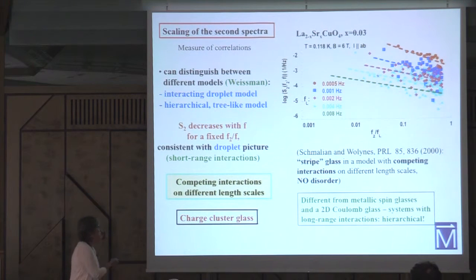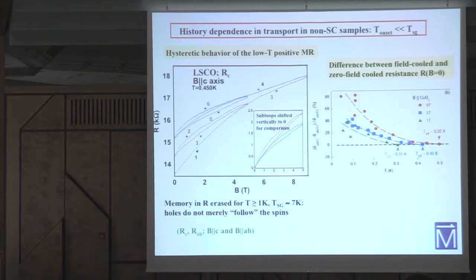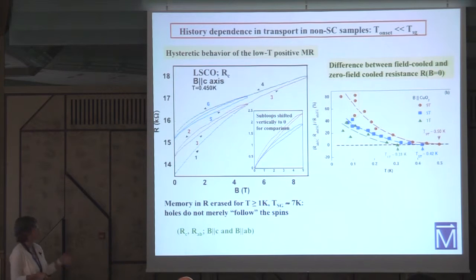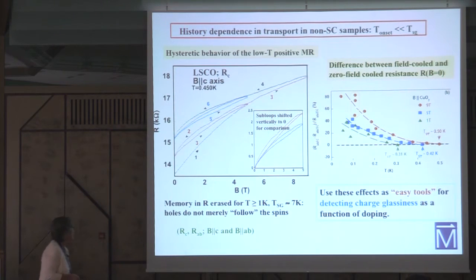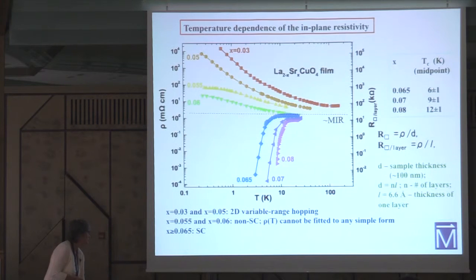In that same regime where we see glassiness, we also see history-dependent hysteretic behavior in transport. There is hysteretic behavior of the magnetoresistance and a difference between field-cooled and zero-field-cooled resistance. Our goal next was to investigate the evolution of this charged glass state with doping as we approach the transition to a superconductor, using both noise measurements and these history-dependent transport experiments.